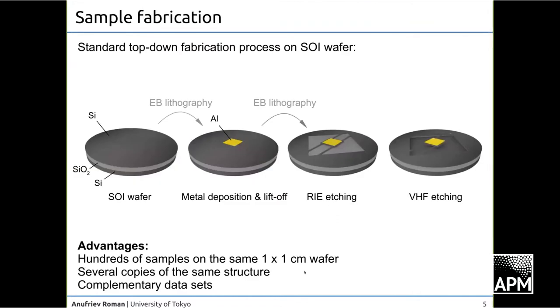To do so, we use a top-down fabrication process to fabricate our samples on silicon-on-insulator wafers. Basically, we start with the insulator and, using e-beam lithography, we pattern aluminum square pads, which will later serve as the heater and the detector of our system. Then we draw nanowires around this pad, so that this part is on an island, which is supported by these nanowires. And then we use vapor etching to etch out the sacrificial layer, so that we have a suspended bridge structure like this, with the island suspended on the nanowires. So the only way for heat to escape from the center is to pass through the nanowire and feel its resistance.